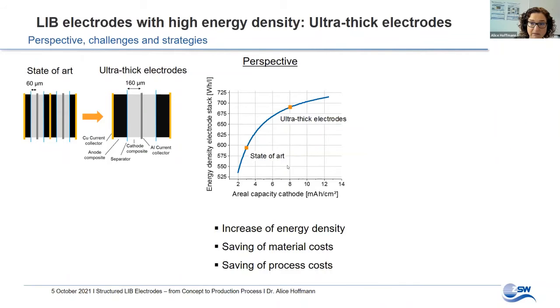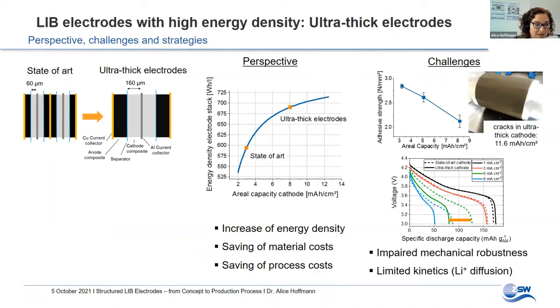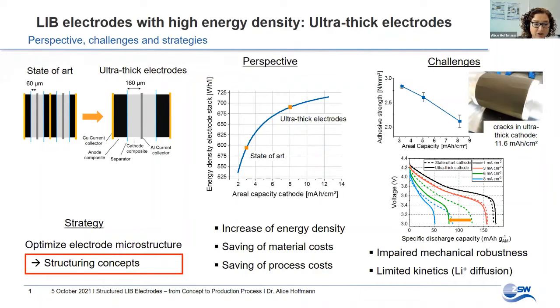However, besides mechanical impairments that you can see here, the adhesive strength decreases with areal capacities, and ultra-thick electrodes have a tendency to build cracks. The ultra-thick electrodes show very low power, which is currently the greatest obstacle for their use in high-energy applications. The reason is their limited lithium-ion diffusion kinetics. One strategy to counteract this limitation is to locally customize the microstructure to enable a fast utilization of more active material. Hereinafter, I will show some structuring concepts that are suitable.